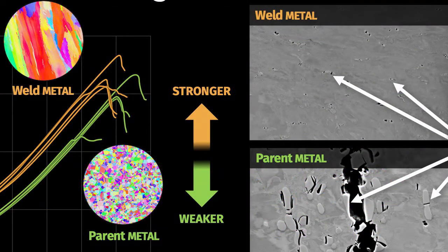Let me now show you some of the results, but before jumping into the discussion on molten salt corrosion performance of the weld and the parent metal, we have to test the strength of the material, because if the strength of the material is not satisfactory, there is not even point doing molten salt corrosion testing. So we have extracted small specimens from both parent and the weld metals and simply loaded them until they fail. And from the results on the left hand side, you can see that actually the weld metal is stronger than the parent metal because it fails at higher applied load.